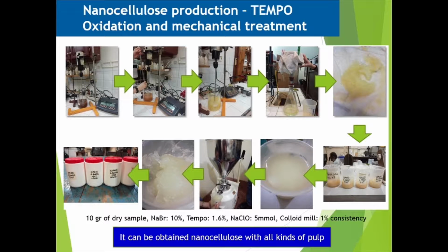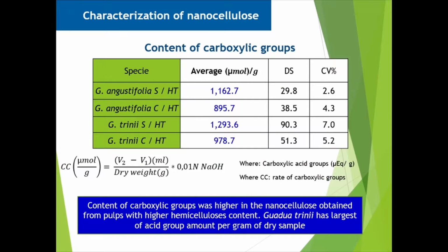The resultant was washed 3 times with 2 liters of water to remove the alkali and brought to 1% consistency, then passed through the colloidal mill 10 times. This nanocellulose obtained was also characterized.